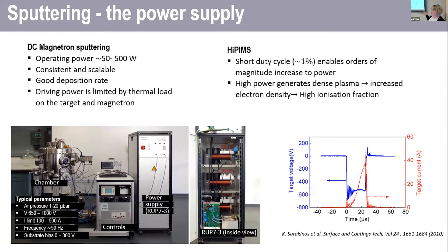So this gives you a very small duty cycle, about 1%. And in doing this, you can see the current that we're accessing is in this figure anyway is 40 amps, but normally this can access current in the hundreds of amps. And this allows you to generate a very high density plasma and increase the electron density.